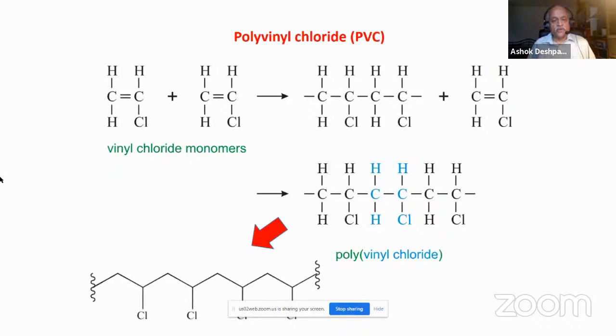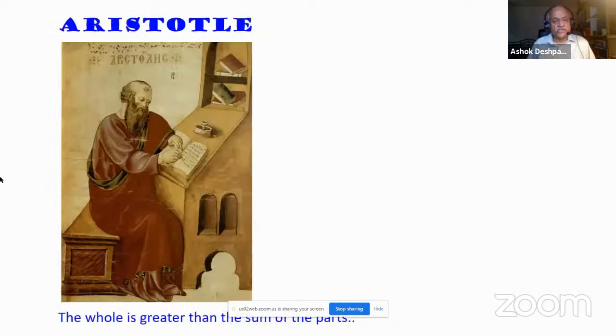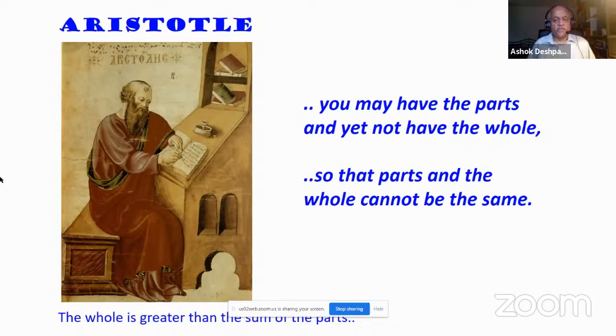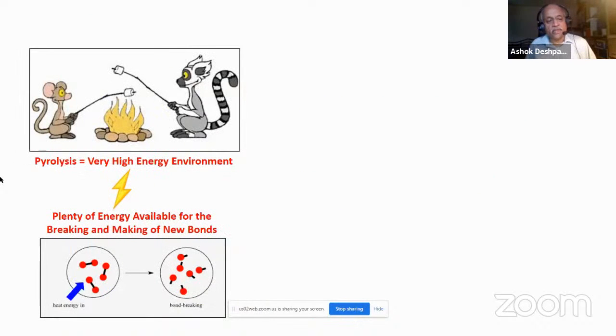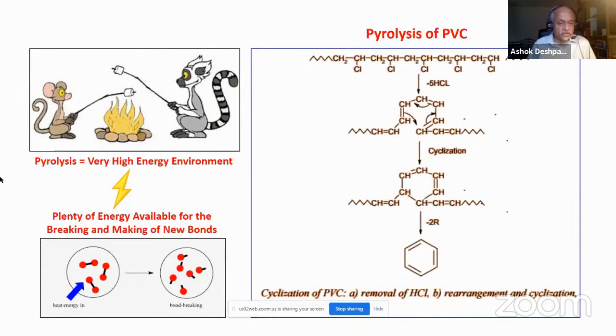It is understandable how we get hydrochloric acid because it contains chlorine, but it is not understandable why it gets aromatic compounds. This reminds me of an Aristotle quote: "The whole is greater than the sum of the parts." So we have the parts, but we cannot explain the whole. We can try to explain this now. Pyrolysis is a very high energy environment, and there is plenty of energy available for making and breaking of the bonds. So the hydrochloric acid is removed from the polymer chain. The bonds rearrange, cyclize, and the side chains are removed to form a stable benzene molecule. So that is the story of the PVC pyrogram.